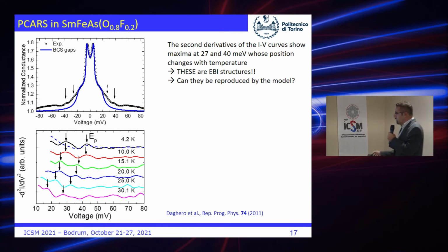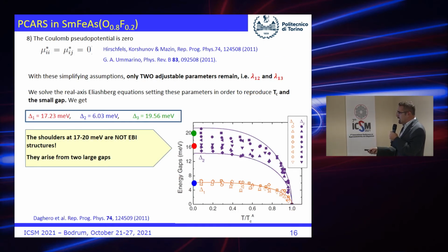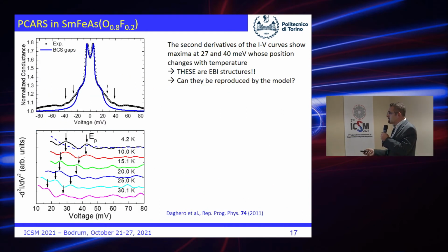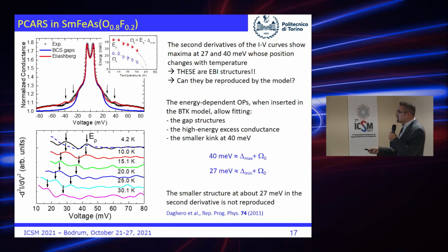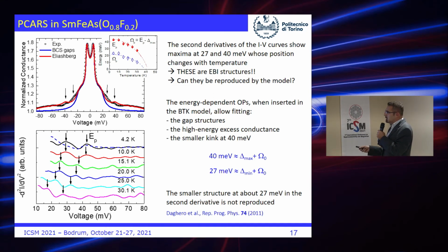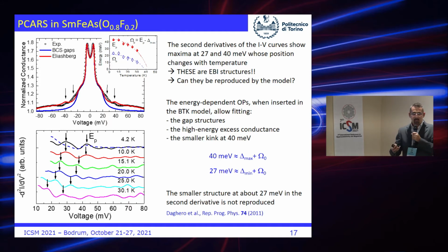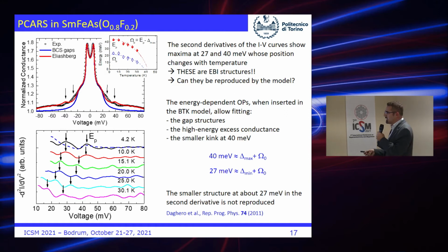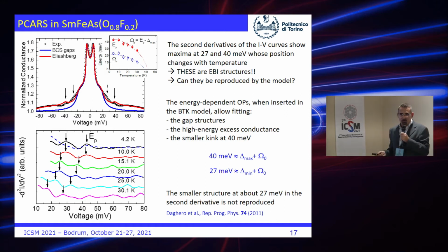Okay, if now we go back to this, we take the energy functions that give the gap, we put them into the big machinery of the BTK model, so we calculate the spectrum. It turns out that we have this result, the red curve. The red curve is very good because not only does it fit the gaps, but it also fits this peak here and this anomaly, that is the excess of conductance at high energy, which, for those who work in the field, is absolutely crazy when you have to normalize the curves, because you don't know how to normalize the curves. But anyway,